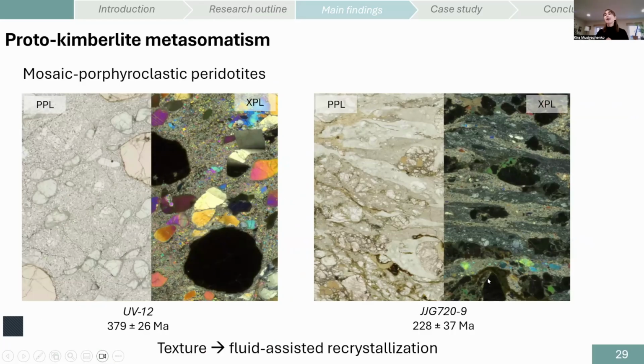These samples display a mosaic porphyroclastic texture, which is commonly interpreted as evidence for fluid-assisted recrystallization under high strain. Compositionally, these garnets are characterized by low chromium and elevated sodium and titanium, pointing to a kimberlite-related metasomatic overprint. The lutetium-hafnium ages obtained for this group place time constraints on fluid-induced weakening of the cratonic mantle, likely associated with protokimberlitic metasomatism. Importantly, these ages are also consistent with the idea that deformation, metasomatism, and isotopic resetting were all part of the same event, preparing the pathway for the kimberlite to go up to the surface.